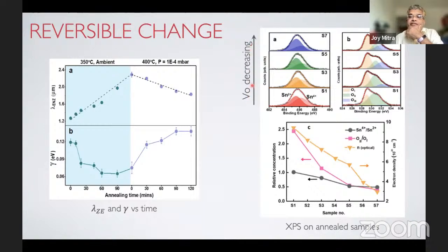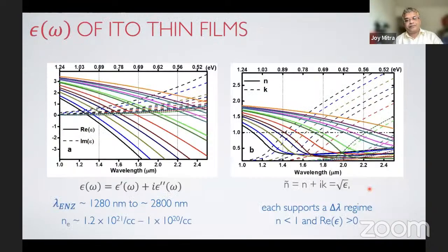A detailed XPS study followed, which showed that indeed, as we were going across the samples quenching the oxygen vacancies, the tin ratio was decreasing. You can see the tin 4+ to 2+ ratio was decreasing. And consequently, the electron density, which is these triangles here, was also decreasing across the samples. And the story made sense. It was extremely reproducible and robust.